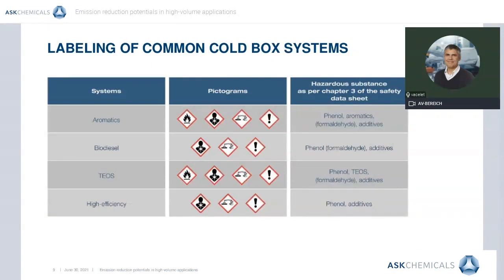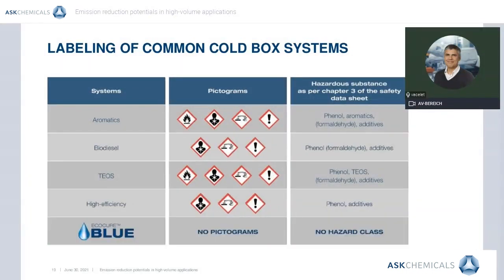If we look at the regulatory labeling of the Part 1 products on the market, we find the same hazard symbol, sometimes with the additional mention of flammability. Whereas the Part 1 of EcoCure Blue has no pictograms and there are no hazardous products to be mentioned under MSDS. This is due to its particular formulation and in particular to the fact that EcoCure Blue Part 1 contains less than 1% free phenol and less than 0.1% free formaldehyde. For sure, the Part 2 still contains isocyanate, which remains to be declared and labeled.